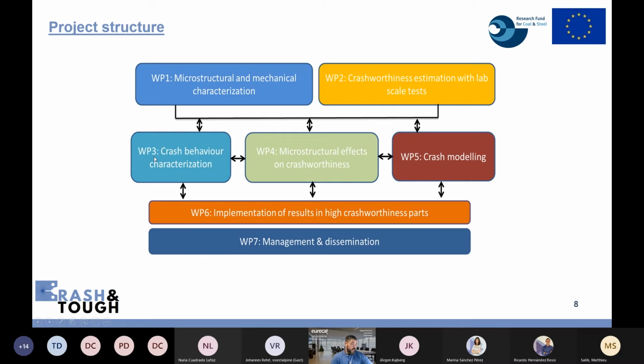Then in work package 3, we performed more semi-industrial laboratory axial and bending impact resistance tests, together with dynamic tensile tests at different strain rates, to characterize the dynamic response of these steel grades. Then in work package 4, we conducted a detailed microstructural investigation by means of different techniques like EBSD and indentation, as we will also see later in further presentations, to better understand the role of the different microstructural constituents of these steels in fracture and crash resistance.